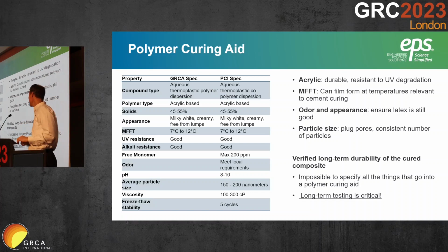We've got at least a dozen acrylic latexes that we make that meet all of these numbers on the PCI spec. It's impossible to specify everything that goes into a polymer curing aid without just specifying it's got to do its job. So there's a dozen of them in our portfolio that meet these specs, but most of them won't work in cement as a curing aid. Some of them will go into cement, but they won't work as a curing aid, and others just plain won't go into cement very well. So that testing is critical, and the long-term testing as well.